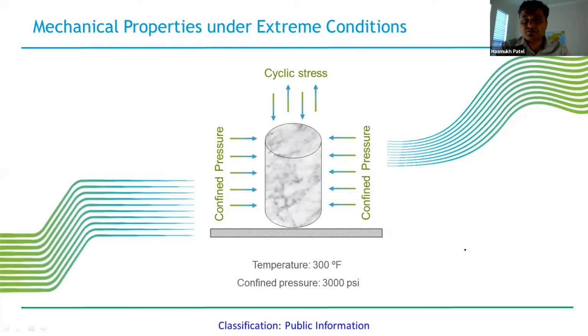The measurement was done at 300 Fahrenheit, which is 150 degrees Celsius, under a confined pressure of 3000 psi. When we applied the axial stress, it went up to about 6000 to 7000 psi. So the overall pressure in the chamber where these samples were placed is more than 10,000 psi at 150 degrees. Those are the conditions we want to make sure our materials can withstand.